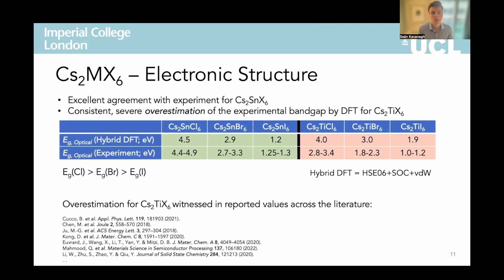When calculating with hybrid density functional theory including spin-orbit coupling effects, which are typically quite accurate in predicting semiconductor band gaps, we find good agreement for the optical gaps of each of the tin-based compounds. We also witness the typical trend of decreasing band gap as we move down the halide periodic group from the small electronegative chlorine to more diffuse iodine. However, for the titanium family, we find a consistent and severe overestimation of the band gap, and indeed this overestimation is witnessed in all theoretical studies in the literature and has not yet been addressed. In many cases, semi-local DFT, which is well known to greatly underestimate electronic band gaps, has been used in order to give fortuitous error cancellation and thus predicted gaps in agreement with experiments. However, in our work we show that this yields qualitatively incorrect absorption profiles and electronic structure. So overall, these findings suggest the presence of some physical behaviour which is not accounted for in our standard single-particle DFT model.